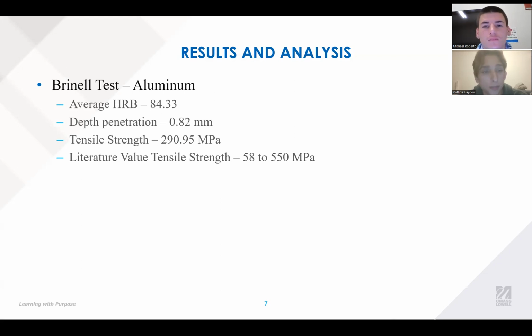But the average HRB was 84.33. The depth penetration, which was on the previous slide, but if you did not catch it, it was 0.82 millimeters. The overall tensile strength is 290.95 megapascals. This is super promising because the literature value ranges from 58 to 550. So we're actually right in that center area, right where we should be, perfectly in the average in between. So that's very encouraging in terms of the accuracy of our data. So overall, the Brinell test is very accurate in terms of how specific you can get the depth relating to the HRB.